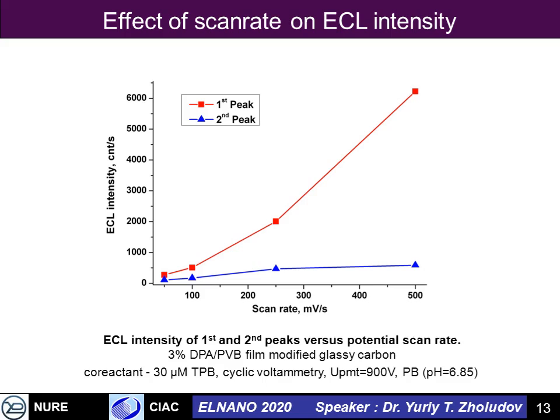When talking about ECL properties of the films made by spin coating, it is clearly seen that another parameter affecting the ECL emission intensity is the potential scan rate. When it increases, the first and second peak intensities increase, but the first peak increases much faster. The second peak increases but shows a kind of saturation. That gives us the idea that the fastest scan rate should be used, or instead of cyclic voltammetry, we can use pulsed electrolysis, which will give the highest ECL intensity.